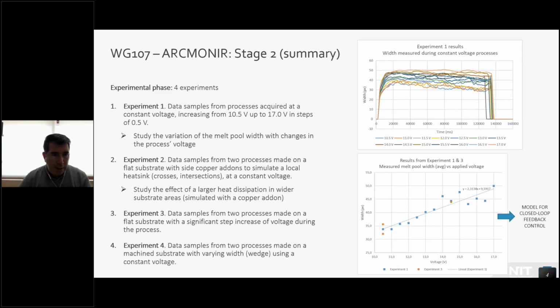For the experimental phase, we designed 4 experiments. The first one was aimed at obtaining data samples from processes at constant voltage. So we defined several voltage steps, increasing from 10.5 up to 17 volts in steps of 0.5. With this experiment, we want to study the variation of the melt pool width measured with our camera when the process voltage changes. These are the curves that you can see on the right. You can see in the upper one how the melt pool width changes as we increase the voltage of the arc.